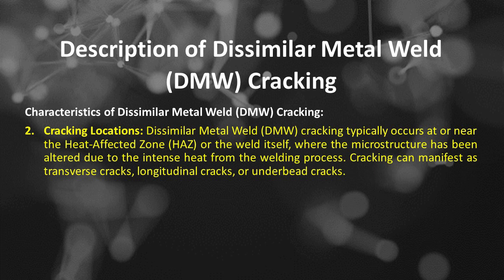Number 2 is cracking locations. Dissimilar metal weld, or DMW, cracking typically occurs at or near the heat-affected zone, HAZ, or the weld itself, where the microstructure has been altered due to the intense heat from the welding process. Cracking can manifest as transverse cracks, longitudinal cracks, or underbead cracks.